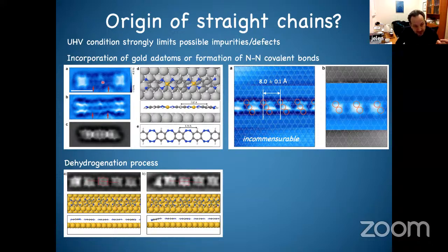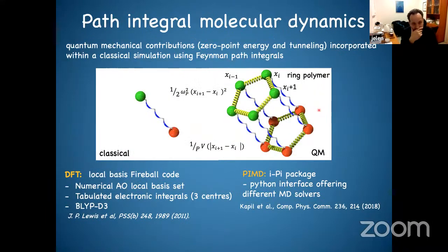But indeed, sometimes we see this gold, or some metal atoms incorporated, but then the contrast is completely different. That's a very rare case, and you see that these high resolution images are completely different, and you really start to see the gold here, which we do not see here. And another thing is that if you have this gold, it will be more commensurate with the substrate. But here, when we do this high resolution imaging, and we can also image the gold underneath, you see that it's incommensurate.